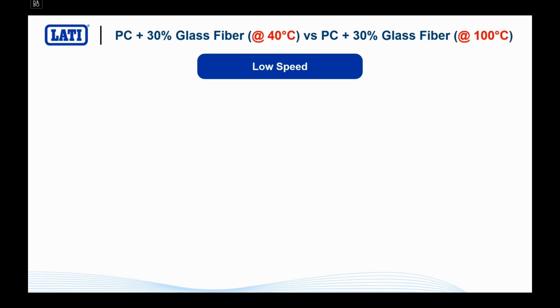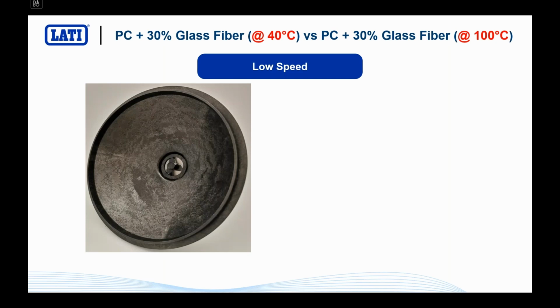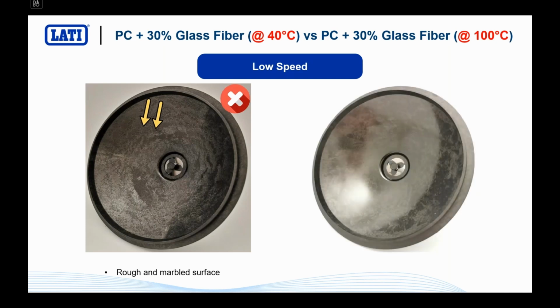So we picked a polycarbonate grade, 30% glass fiber filled, and we wanted to inject it at low speed and then move the speed up, but with two different temperatures, 40 degrees C and 100 degrees C. Here is how it looks with 40 degrees C: extremely bad, very rough, very marbled, a terrible looking part, so totally unacceptable. This is how it looks with 100 degrees C. You see the gloss is vastly increased, and it is really improved, I would say.